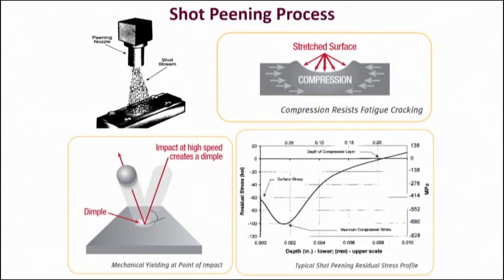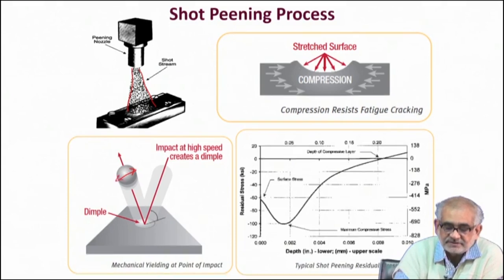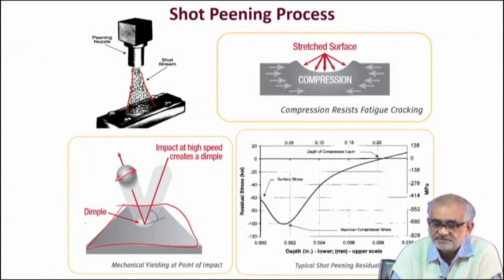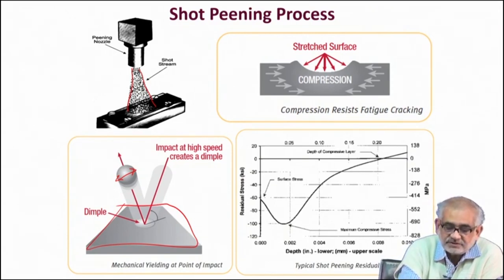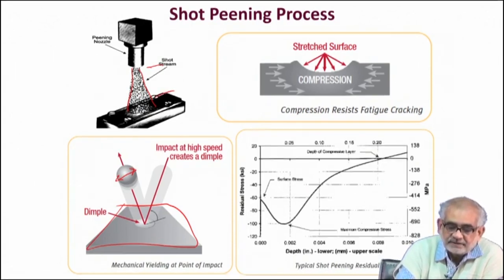The shots are very small compared to the overall surface being treated — less than a millimeter, maybe 0.3 to 0.4 millimeter — while the surface area can easily be a meter by meter or half a meter by half a meter. A gun is required to throw these projectiles with a slightly divergent projection. The distance, velocity, size, weight, material of the shots, surface condition, and angle of incidence all determine the resulting state of stress.